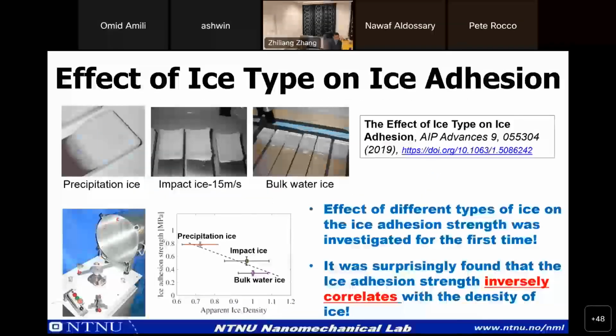So we collaborated with AMIL in Canada, Chicoutimi, and we fabricated 3 types of ice. We have precipitation ice, we have impact ice with the speed of 15 meters per second, and we have bulk ice. These ices have different density. Bulk ice has the largest average density, impact ice is in the middle, and precipitation ice has the lowest density.